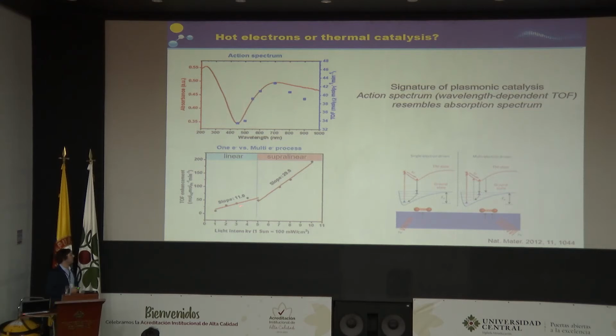So we have a change from a linear dependence of the rate of hydrogen generation to a supralinear dependence. In this case, this has been reported to be due to the switch from a regime where just one electron is excited and used in the reaction to a regime where multiple electrons participate in the reaction. And this, of course, is really the gain of plasmonics.